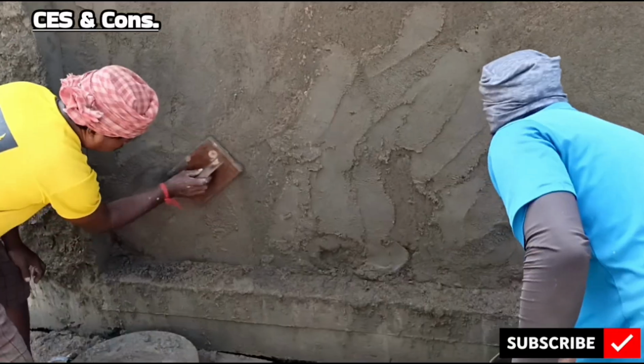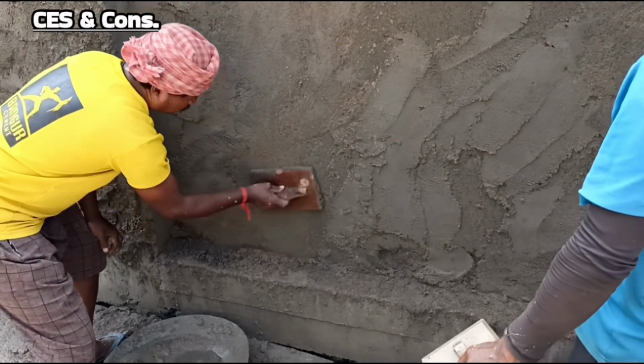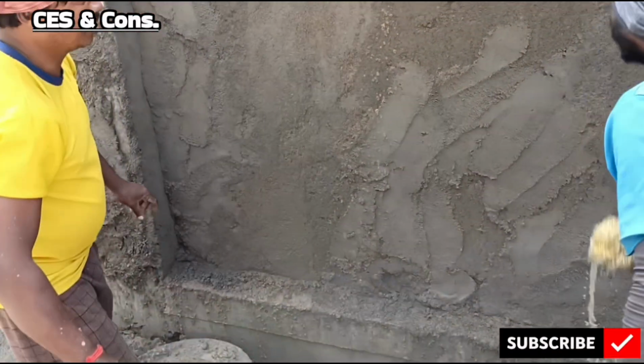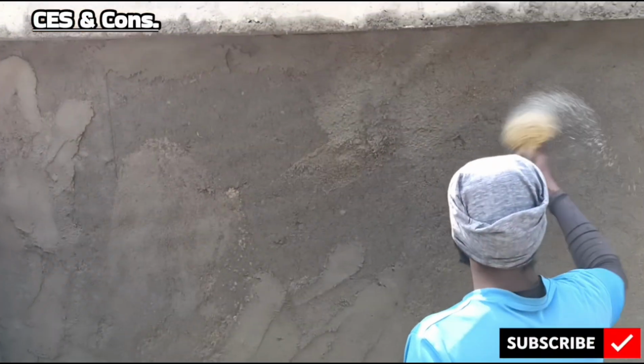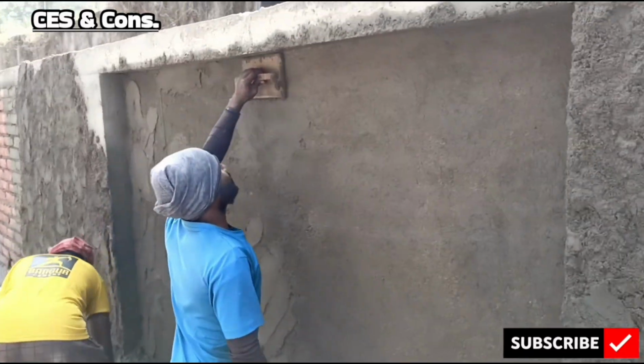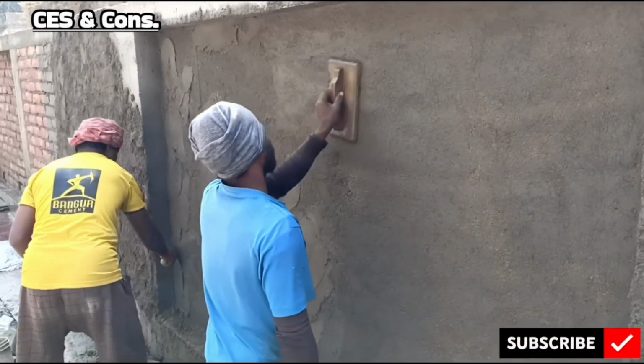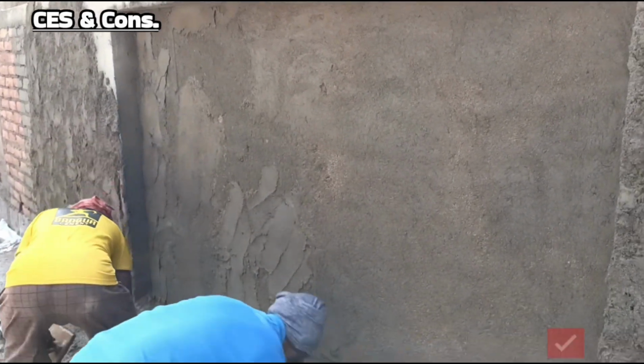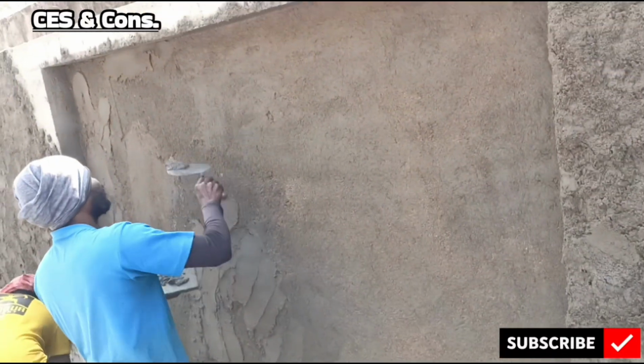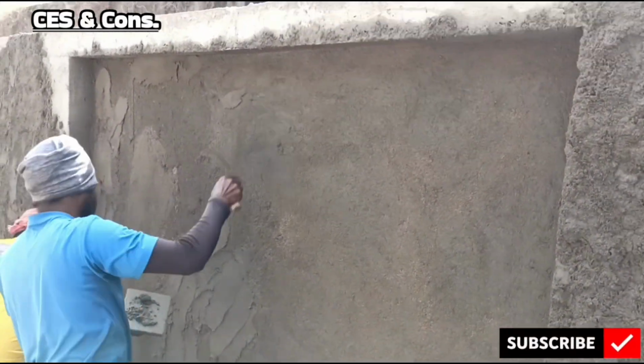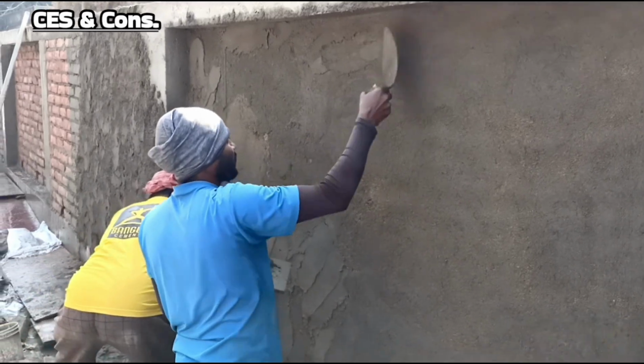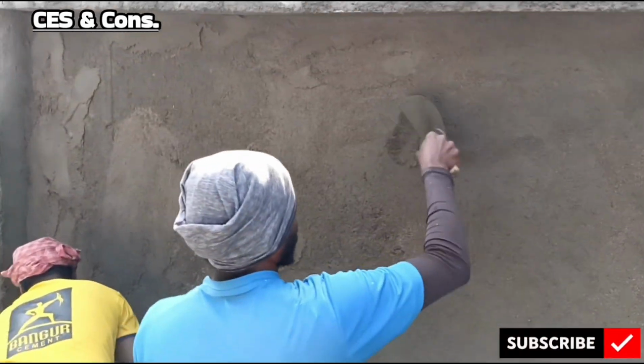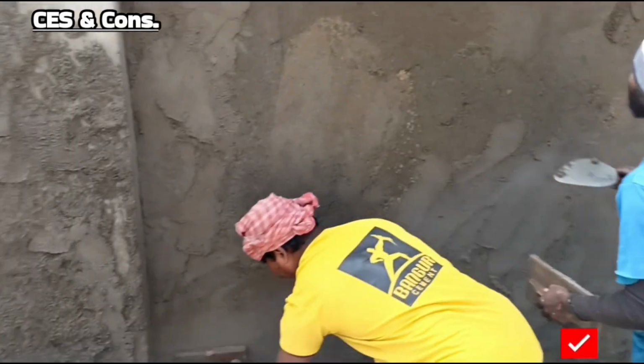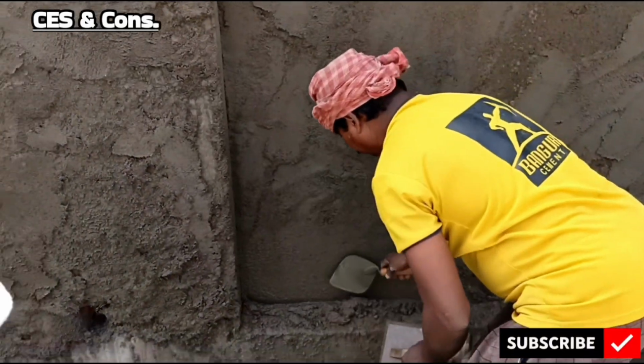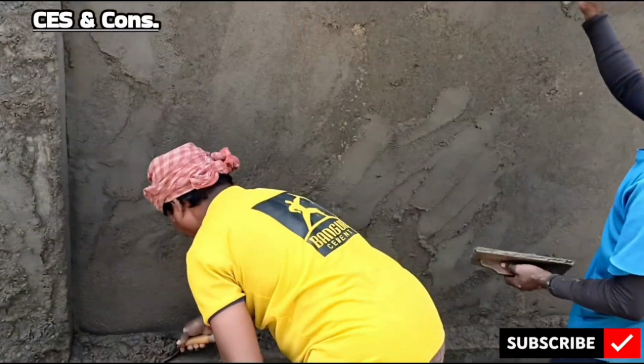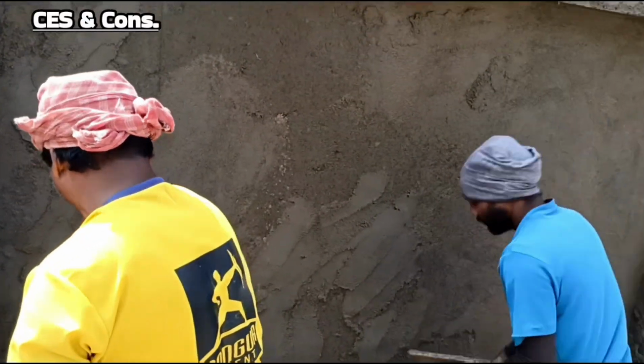Finishing the surface. Finishing can be smooth, sand-faced or textured depending on the requirements. Over-troweling should be avoided to prevent cracks. Curing of the plaster. Curing is extremely important in plaster work. As per IS 1661-1972, curing should begin 24 hours after plastering and continue for at least 7 days. This prevents cracks, shrinkage and loss of strength. Curing is generally done by sprinkling water or covering the plastered surface with wet Hessian cloth.